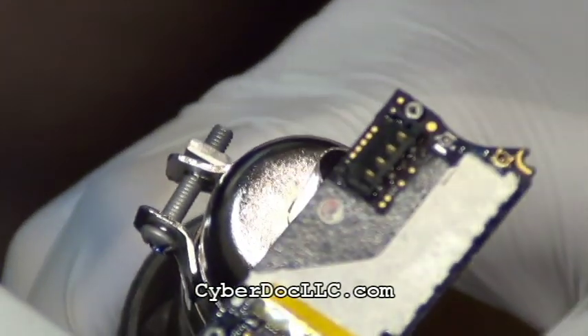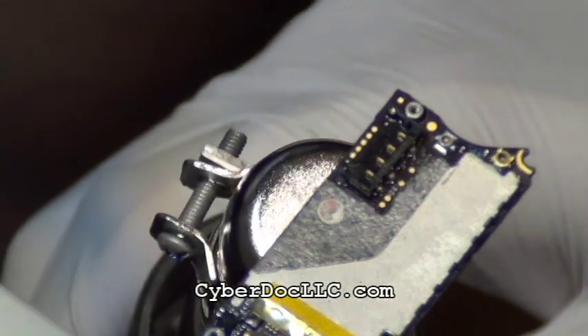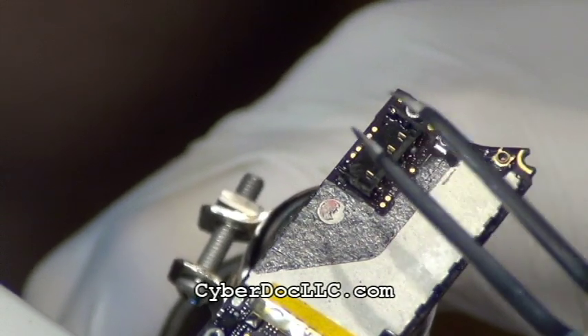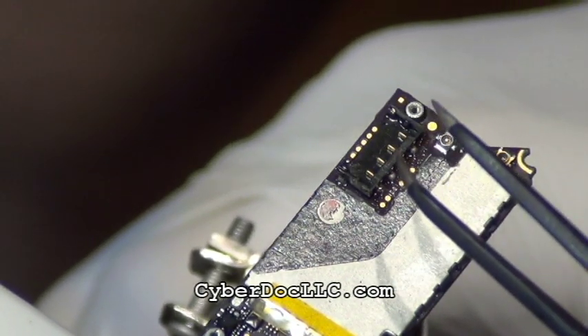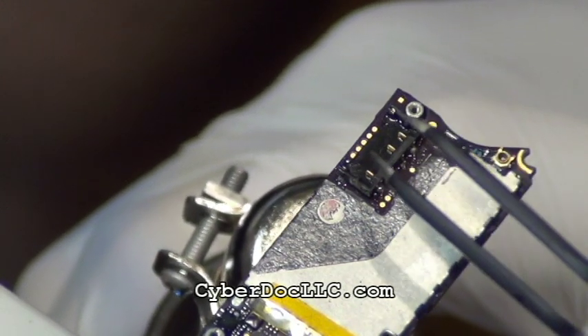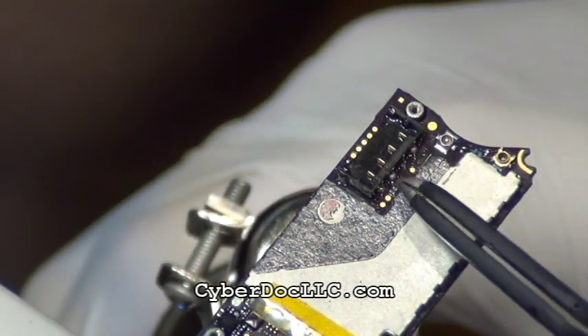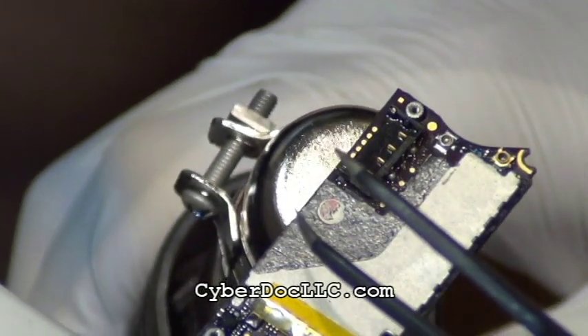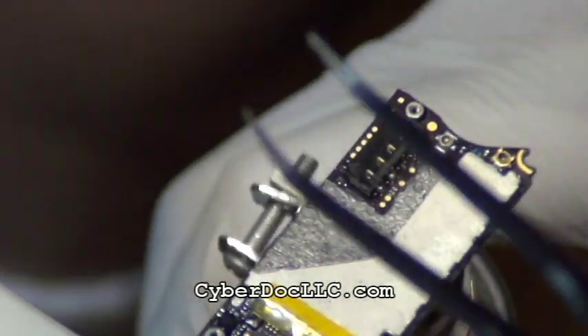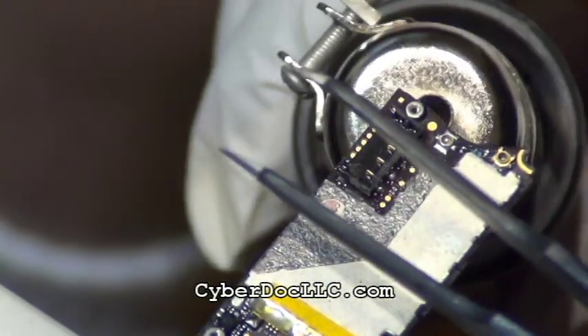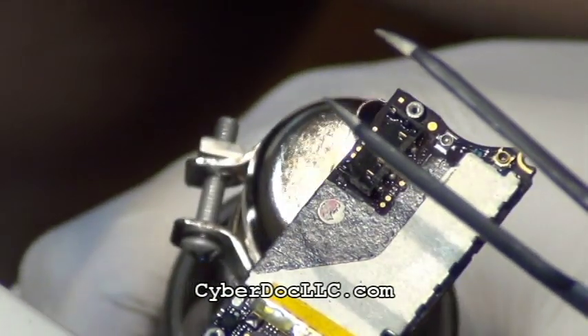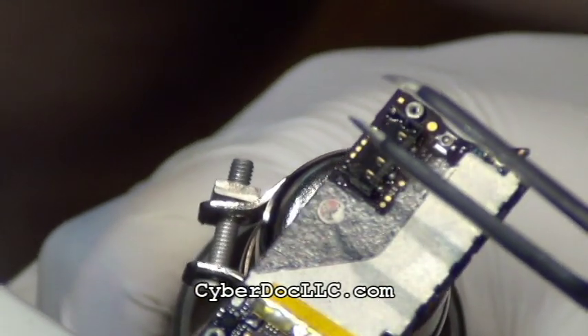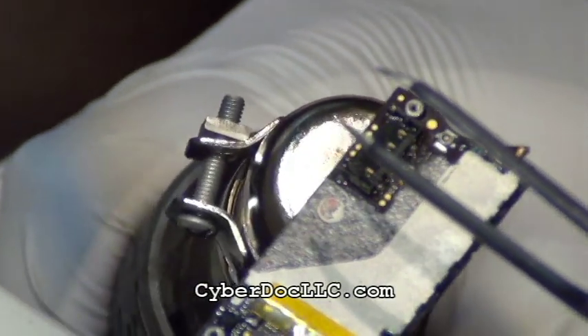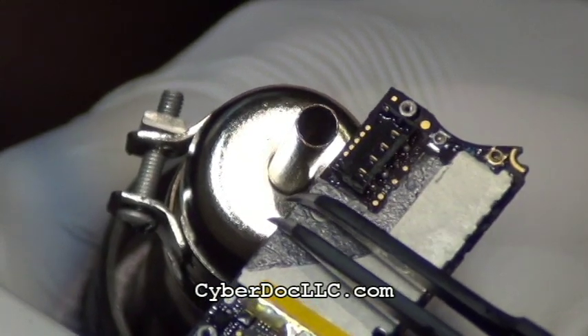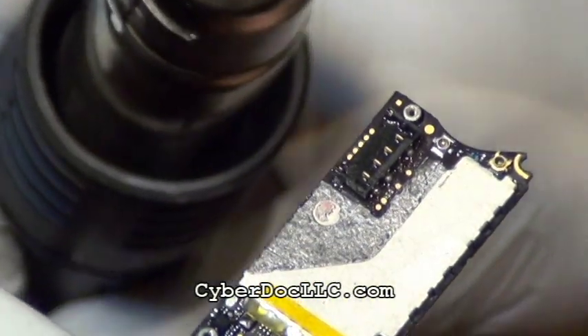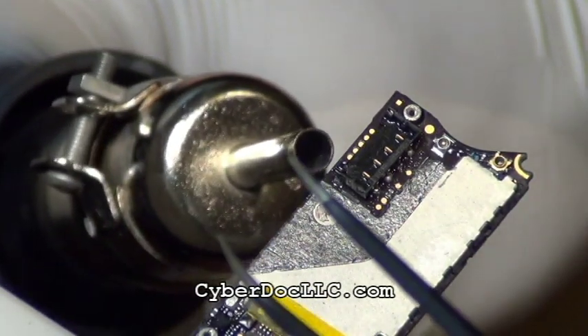Oh, by the way, my hot air gun right now is probably set at 300 degrees Celsius-ish. But if you actually measure the temperature the logic board is getting, it's much lower than that, because the measurement you see on the rework station is measuring inside the ceramic heating element in the hot air gun. Hence, it's going to be a lot hotter inside than outside. I'm keeping the hot air gun on high speed, because low speed will take too long, and the wind at high speed will lower the temperature dramatically by the time it leaves the nozzle.